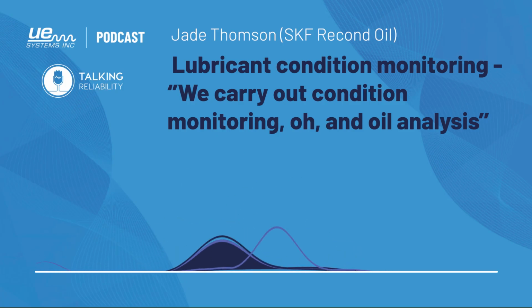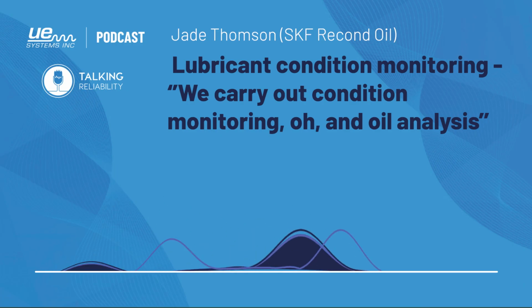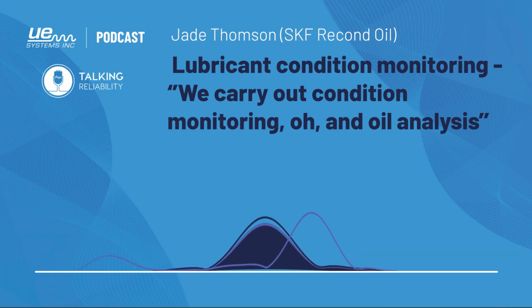So what happened is one of the bearings on one side of each cab of this train had been corroded by the phosphorus additive almost immediately, to the point where all the trains that had oil changes done, which are shown on the bottom, you can see how erratic the copper is on the right, because some of the bearings were fine, whereas others weren't.